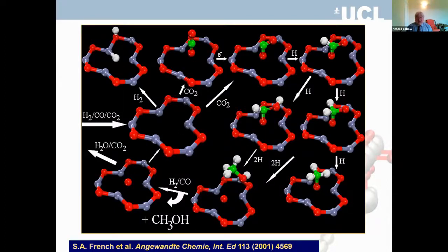Now, in work 20 years ago, we studied some of the basic aspects of the mechanism here. We were studying the process initially just on the surface of zinc oxide, and what we identified as the key process were capture of CO2, which you see in the graphics, and dissociation of hydrogen. Capture of the CO2 at trapped electron sites on the surface activates the CO2 molecules, which then react with hydrogen, and eventually you get methanol formation. And then you oxidize in the final step CO to CO2.